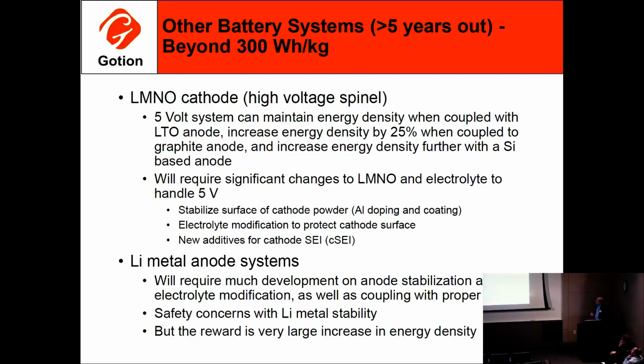But of course, with high voltage, the fact is that you get more degradation of the electrolyte. So you've got to protect the cathode, as I mentioned earlier, with aluminum doping and coating or other metals. And then you also have to protect it with a cathode SEI, but you also have to look at your electrolyte. So is our carbonate-based electrolyte going to be good enough for 5-volt? Maybe, if you get the right coatings on the anode and cathode, it is, and maybe if you don't, then you've got to go to other solvents, fluorinated solvents, and different materials like that.